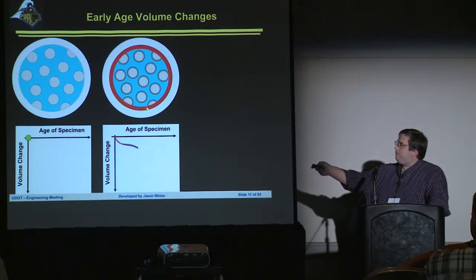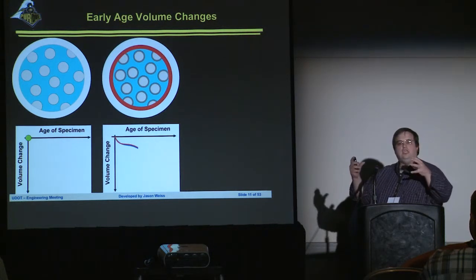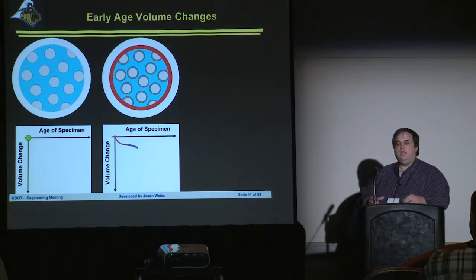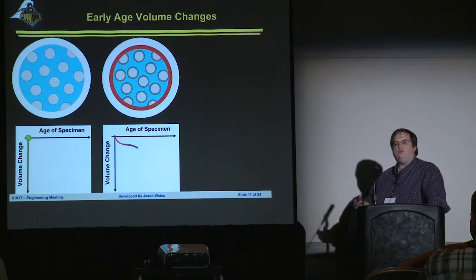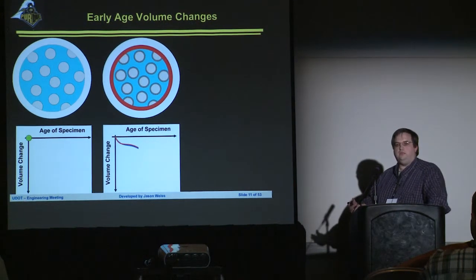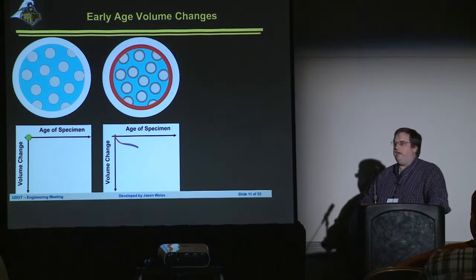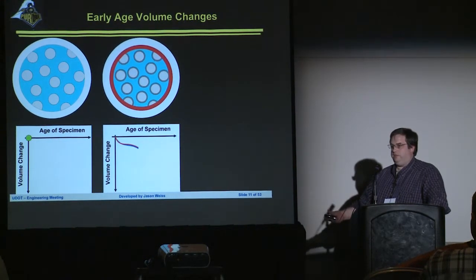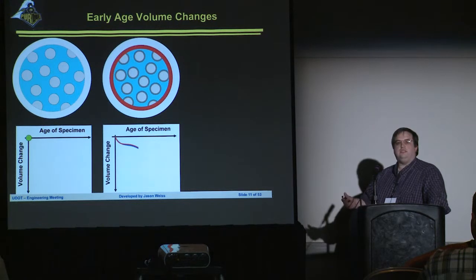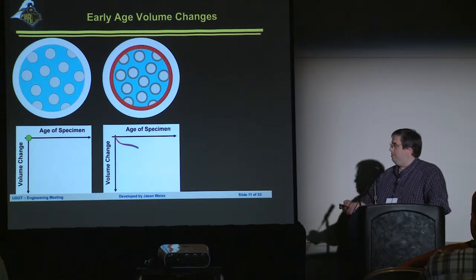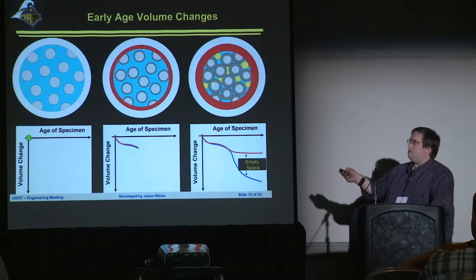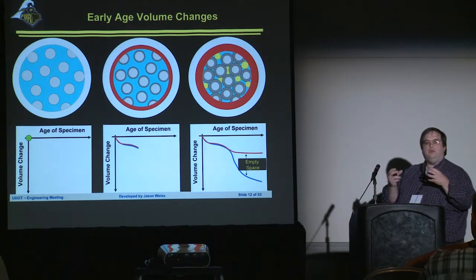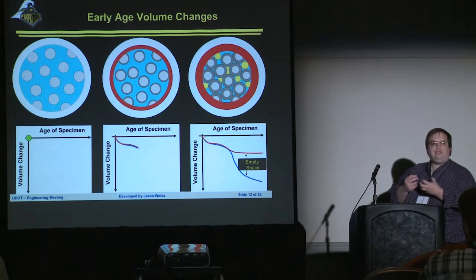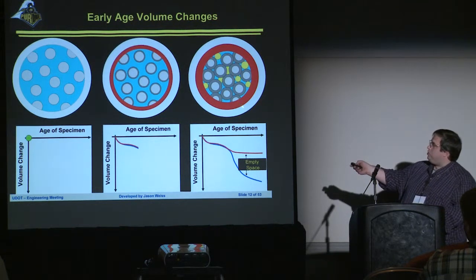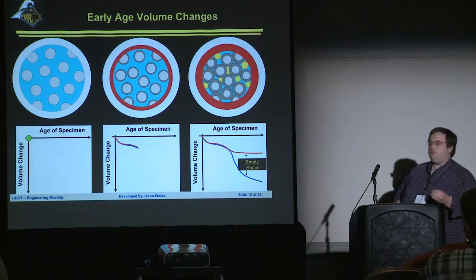Now, when the system is fluid, the system just keeps collapsing upon itself. At some point, these particles can no longer continue to collapse upon themselves. And we commonly refer to that time as setting. At some point, the system ceases to be a fluid and starts to become a solid. So all of a sudden, as these particles begin to impinge upon one another, they can't continue to collapse, and the external volume change now starts to differ from the chemical shrinkage that's occurring.